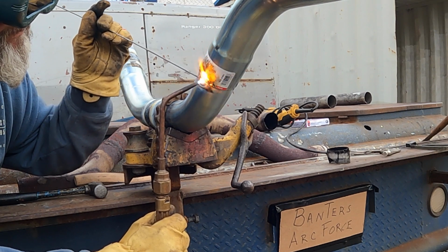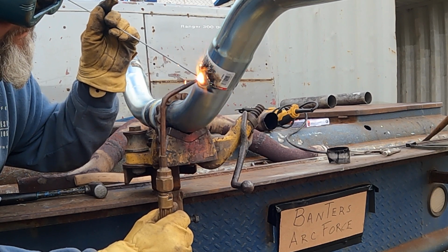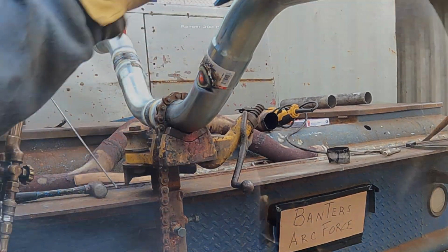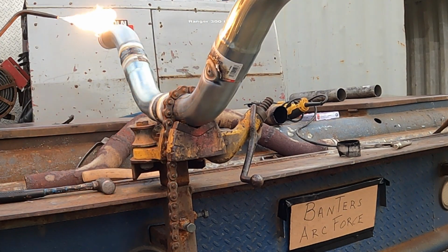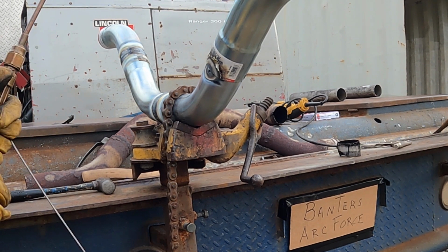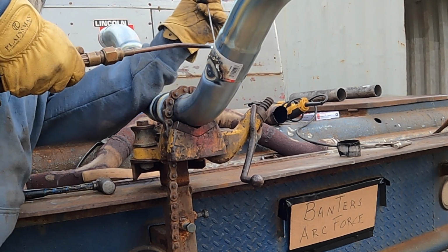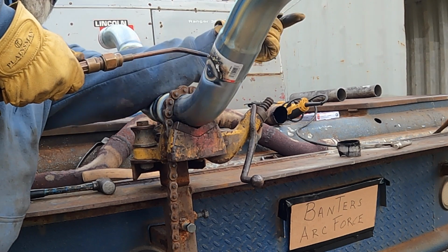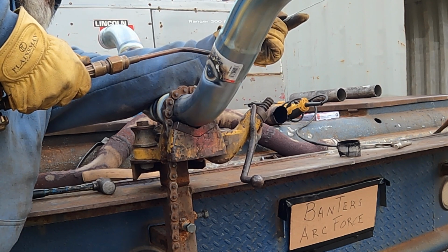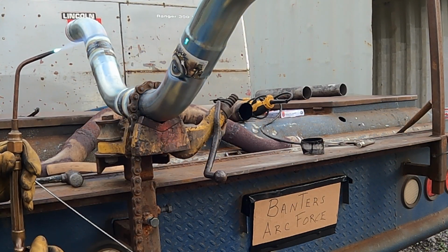The newer piping today is like X52 and up, and if a person is going to do oxyacetylene welding on natural gas piping, it's because the pipe needs to be X42 to X52. The welding rod is R60, which stands for 60,000 tensile strength. And today, with the X52 and up, they want you to use 6010 or 7010 and up, and it can't always be used because they're standard. But on services, if it's a lower grade pipe, it can be used.